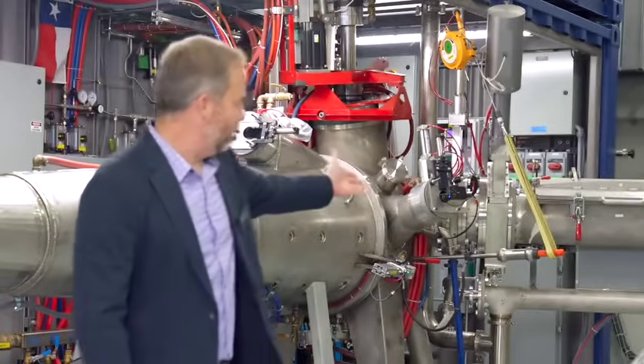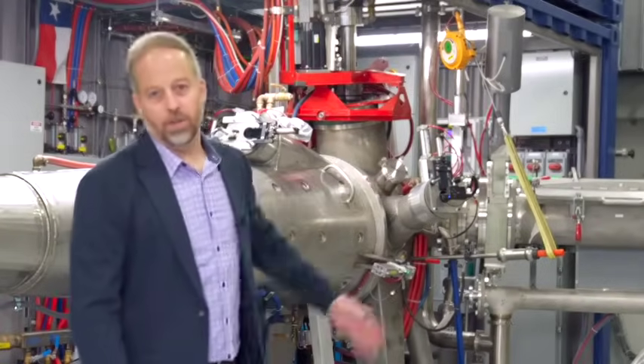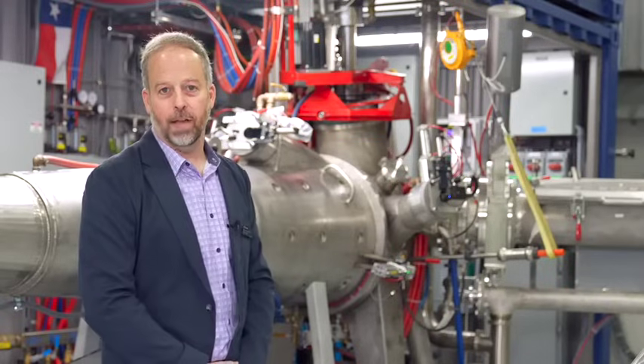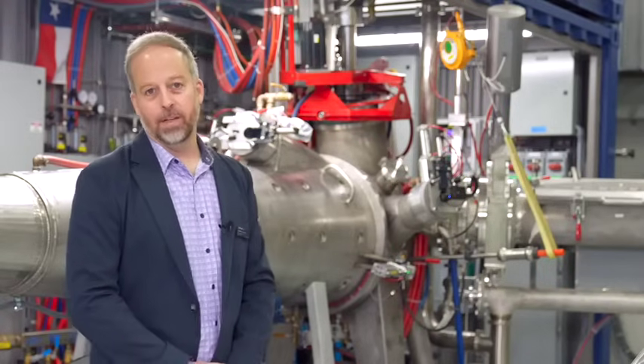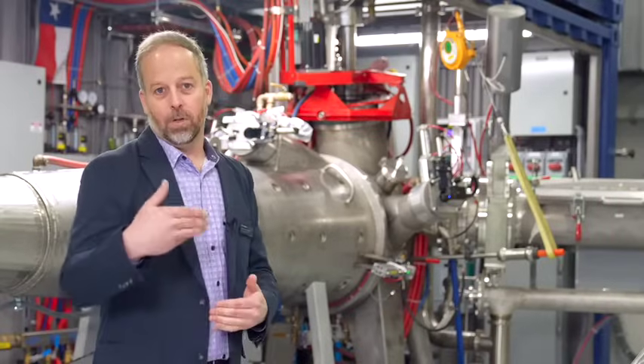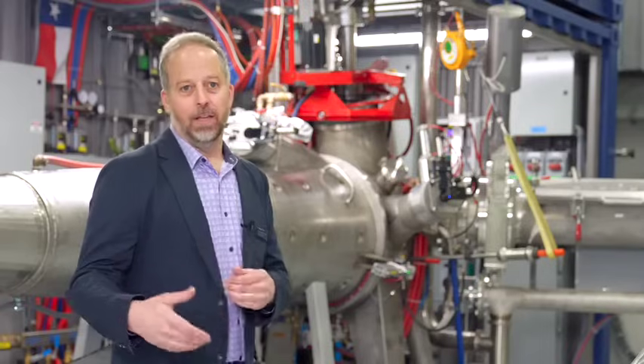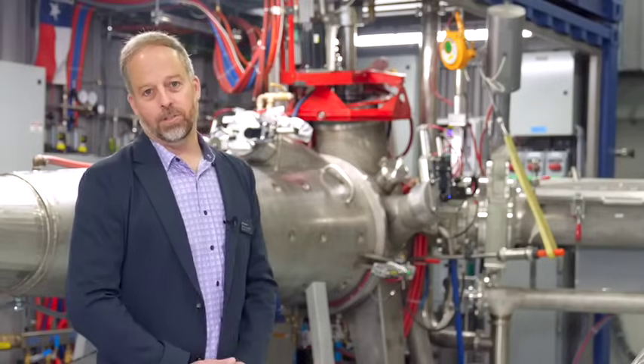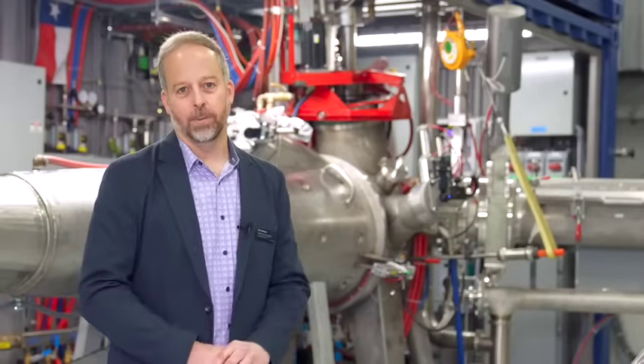The feed materials go in this feeder here. This is a load lock feeder, which allows us semi-continuous operation throughout the day without inhibiting the chamber atmosphere. So we can keep adding material, pumping it down, inerting it, and feeding it into the machine all day long. That allows us to produce quite a bit more material with a smaller atomizer than you'd see in the industry typically.